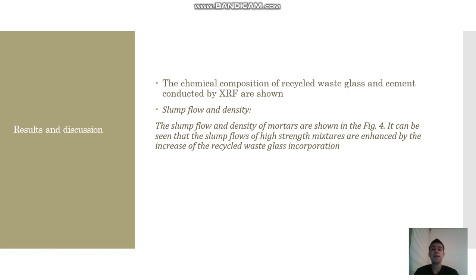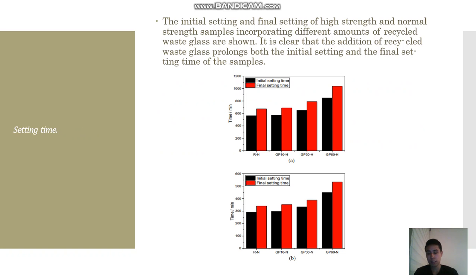The chemical components of recycled waste glass and cement, conducted by XRF, are shown. The slump flow and density of mortar are shown in figure 4. It can be seen that the slump flow of the high strength series increases with the incorporation of recycled waste glass. The initial setting and final setting times of high strength and normal strength samples incorporating different amounts of recycled waste glass are shown. It is clear that the addition of recycled waste glass prolongs the initial setting and final setting times of the samples.